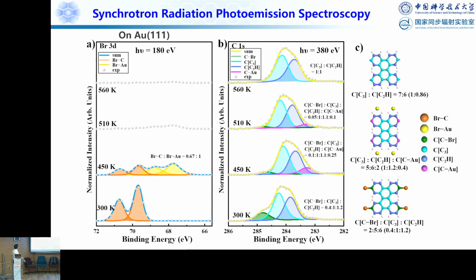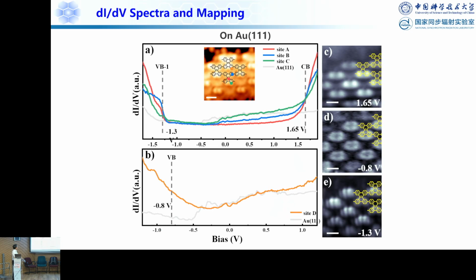Okay, and this STM and this XPS again help to understand the reaction mechanism. This is measured at our synchrotron radiation photoemission station, and the result is really consistent with what we observed. We propose the atomic structure. Okay, and now we measure the electronic structure over here. The band gap is about 2.9 eV, and this is the mapping.